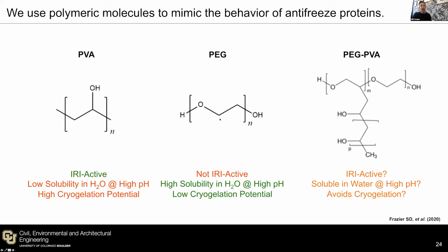We took note of PEG, polyethylene glycol, that had the benefits that PVA did not. The only downside with PEG was that it was not IRI active. So we thought if we combined the two into a copolymer, we would either get the best of both worlds or the worst of both worlds. And fortunately, we did get the best of both worlds. So we did prove, and I'll show you some data, that PEG-PVA is IRI active at high pH. We can dissolve it in water, and it gets us the performance that we wanted.